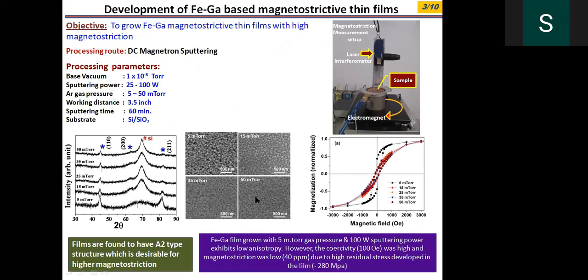We have found that the magnetization measurements show the coercivities to be high. To understand the reason, we found the stress levels to be very high. The stress levels are found to be around 280 MPa.